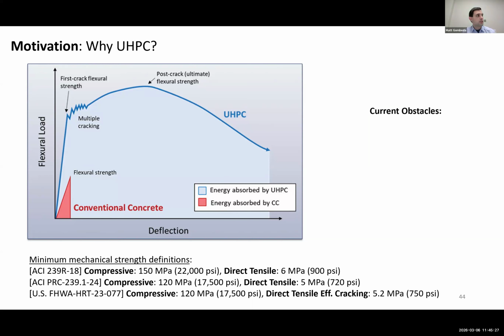But the current obstacles are not so much on the strength side. The proprietary nature makes things more expensive, and non-proprietary mix designs require a little bit more thinking and frameworks. There's still a relatively high cost associated with these mixes. Mix times are too long, and workability retention is a huge issue. Having the flow met right out of the mixer is one thing, but then you come back 10 minutes later and we get things like skin formation, and the mix really starts setting very quickly and it's hard to finish, which is a problem.